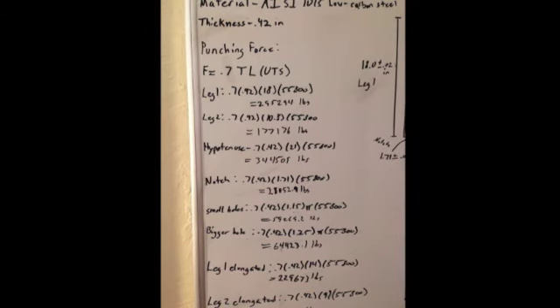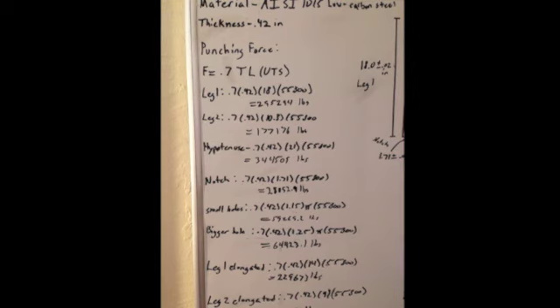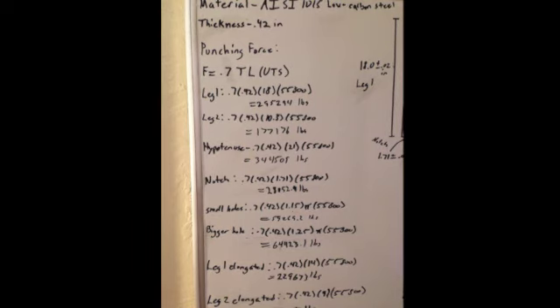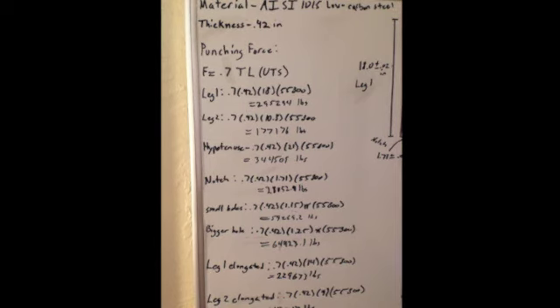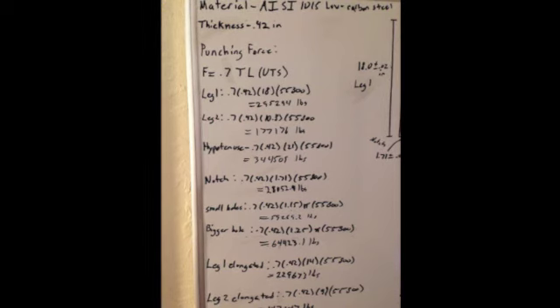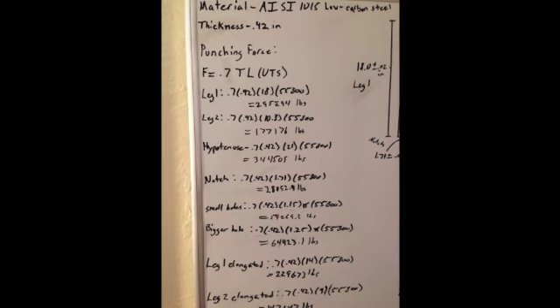Here are our calculations for our punch force regarding the perforations for our holes. We used the punch force formula we found in the textbook. It's 0.7 times the thickness times the length times the ultimate tensile strength of our chosen steel. As you can see, the larger the hole, the greater the punching force, which is why we decided to punch the smaller holes last, so as to not deform them in the punching of the larger holes. We're trying to minimize deformation of the holes being created.